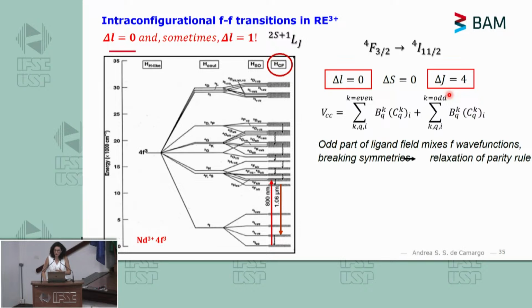It happens because the ligand field here, I told you, does not influence too much the electronic levels, but it influences enough to perturb the system so that the parity of the wave functions is not so well defined. So it's actually the odd part of the electric field of the ligand field that will perturb the wave functions F, and then the symmetry will be broken. Once the symmetry is broken, there will be some even parity, and then we say that the selection rule is relaxed. Okay? So now we can have delta L equals 0.